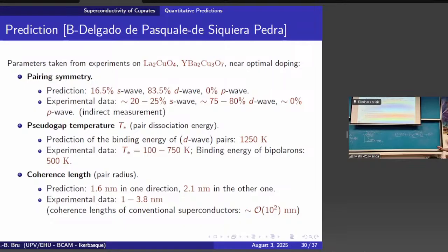And this is also very coherent because in conventional superconductors, the coherence length is very big. It's a few hundred nanometers, which we do not find here. And this has to be related to the theorem I presented, that these pairs are exponentially localized. I have a theorem that says the pair wave function is exponentially localized, so it should not be big. So that's what we find here.